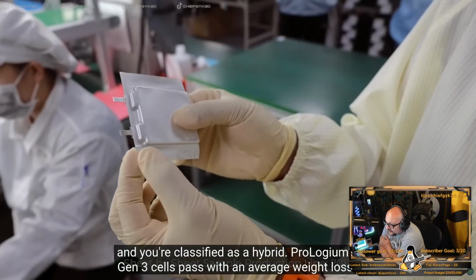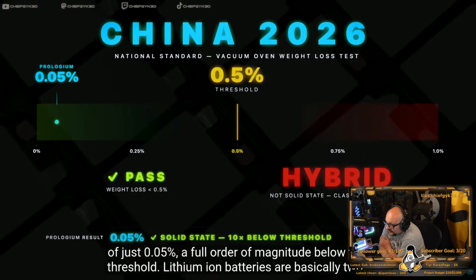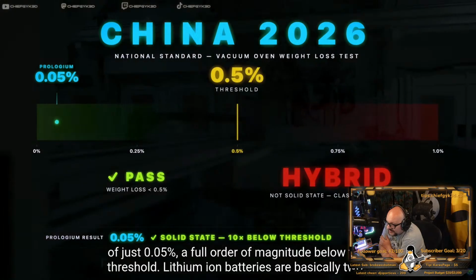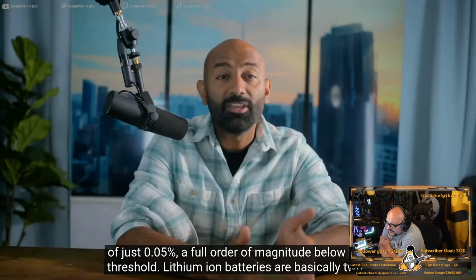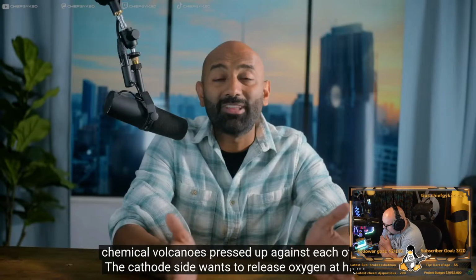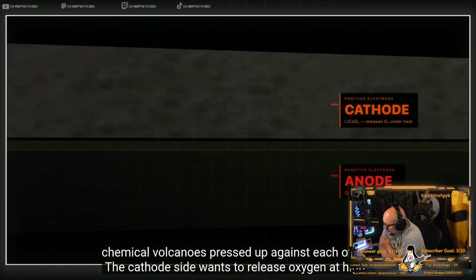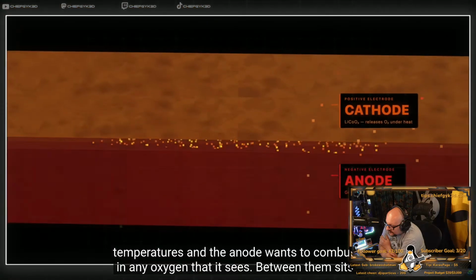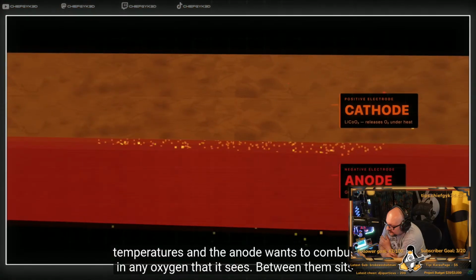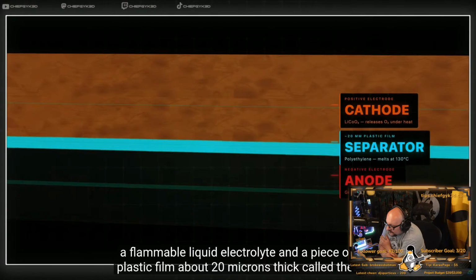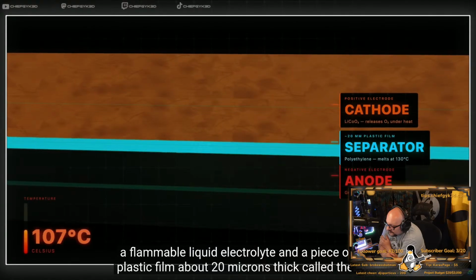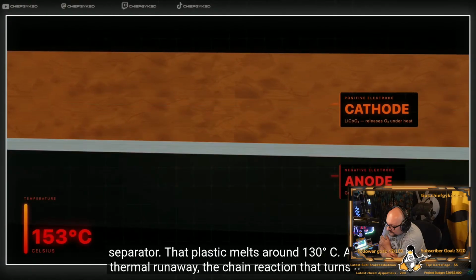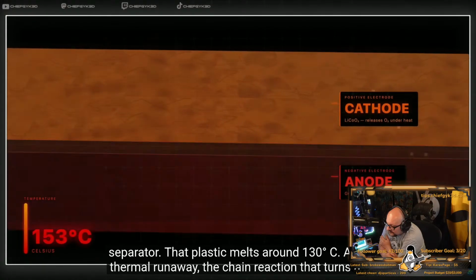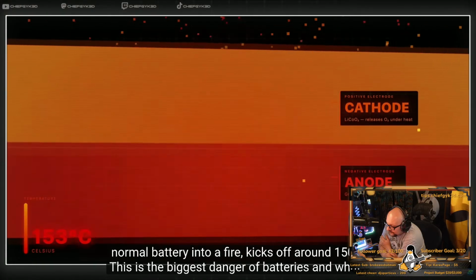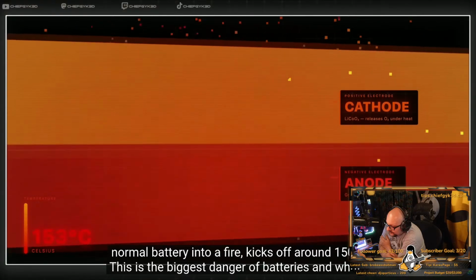Prologium's Gen 3 cells pass with an average weight loss of just 0.05%. Jeez! Order of magnitude below the threshold. Lithium-ion batteries are basically two chemical volcanoes pressed up against each other. The cathode side wants to release oxygen at high temperatures, and the anode wants to combust in any oxygen it sees. Between them sits a flammable liquid electrolyte and a piece of plastic film about 20 microns thick called the separator. That plastic melts around 130 degrees Celsius, and thermal runaway, the chain reaction that turns a normal battery into a fire, kicks off around 150 degrees Celsius.